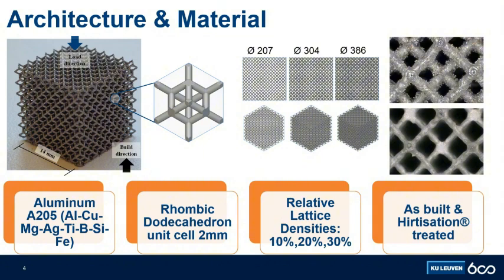The relative lattice densities, the nominal ones manufactured in this way, were 10, 20, and 30% relative density, as you can see here. And the upper parts are the diameters in micrometers for each category. And the main categories for comparison were the as-built on top and the Hirtisation treated on the bottom.